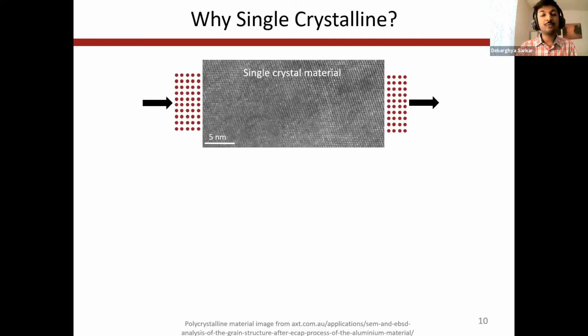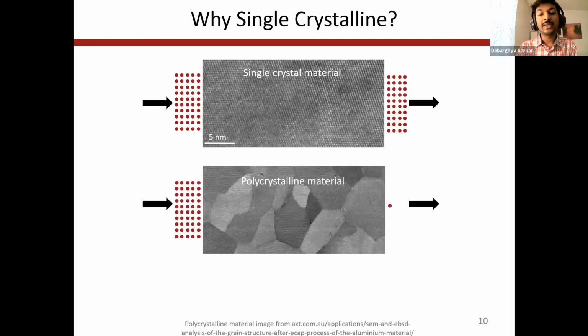Well, a simple example would be that if we, let's say, inject 50 electrons on one side of a device comprised of a single crystal material and expect to receive, let's say, 40 electrons on the other side, retaining the same velocity as in the injection side, then with the same experiment, we would possibly get 1 electron if we do that with a polycrystalline material, simply because there is a lot more scattering that happens at the grain boundaries.